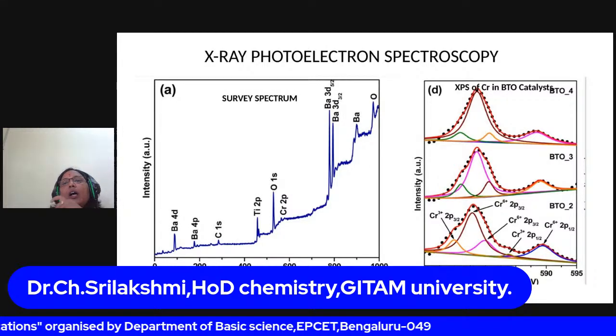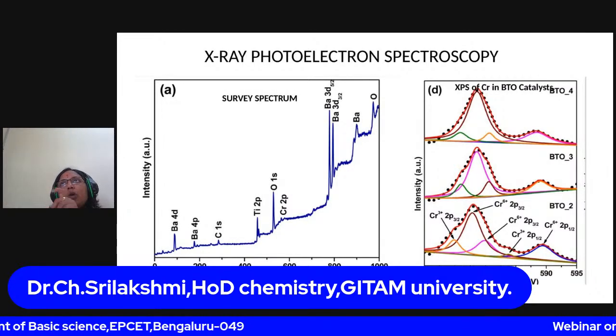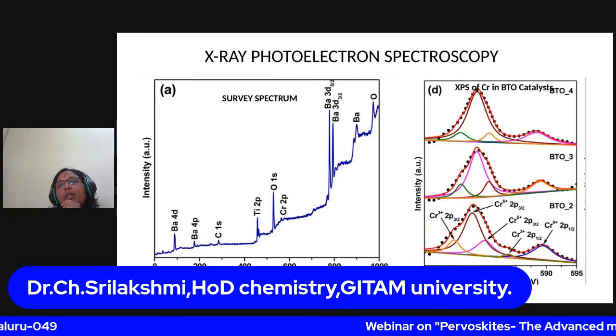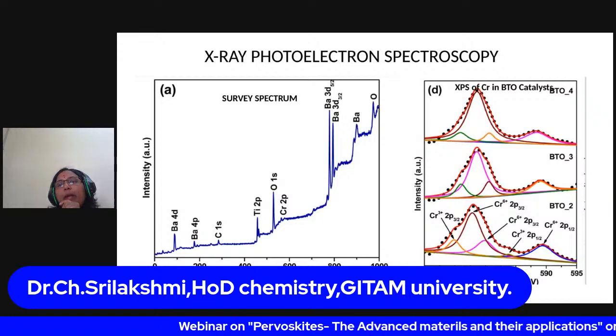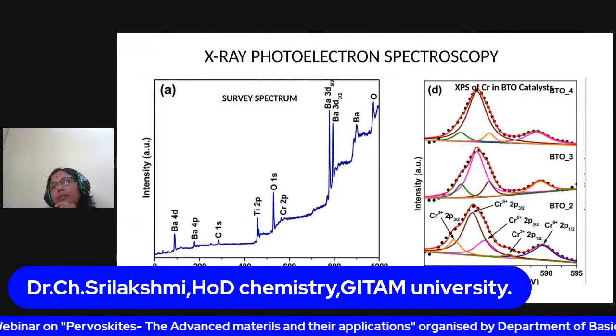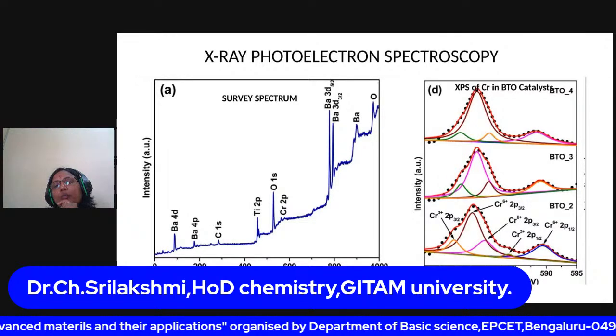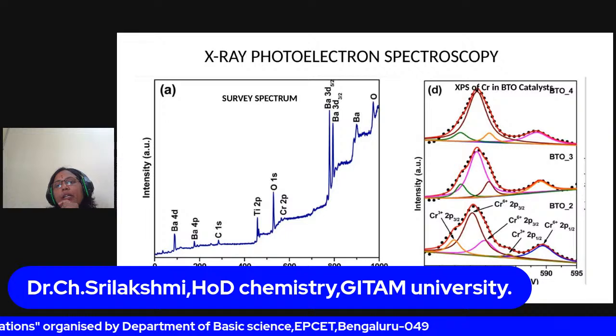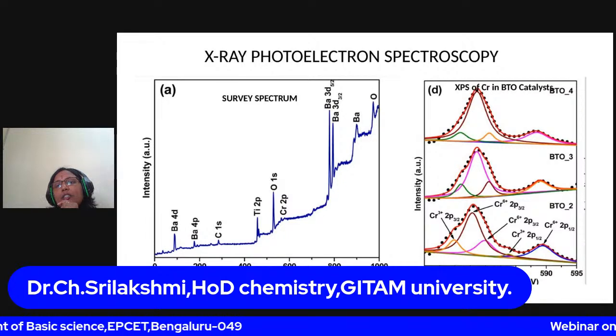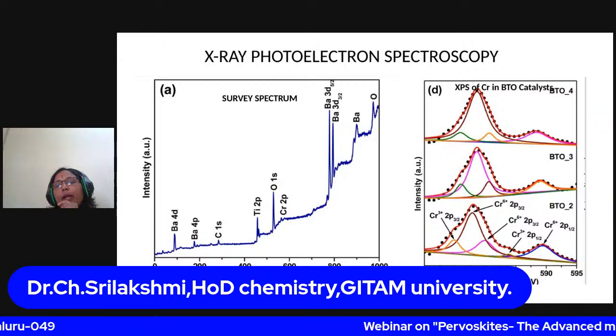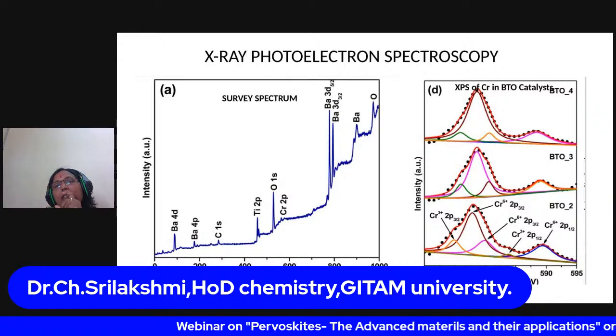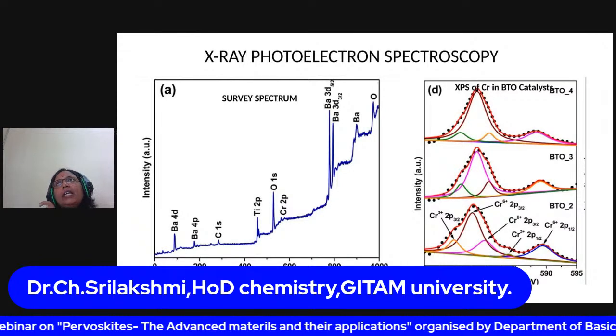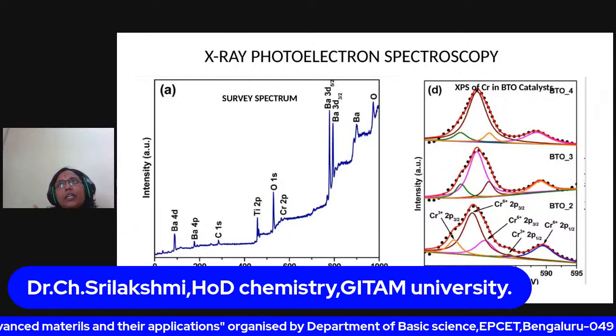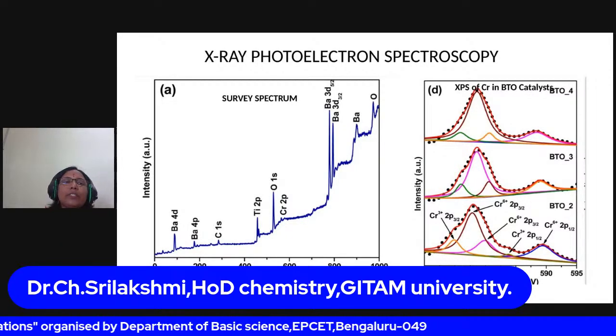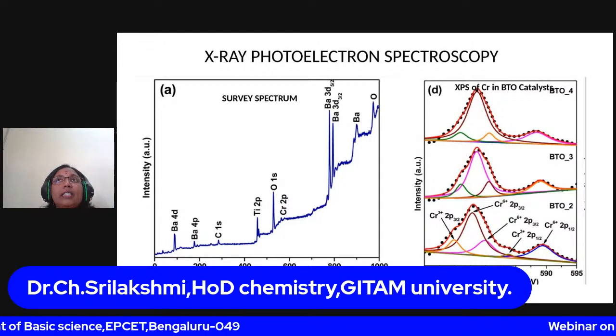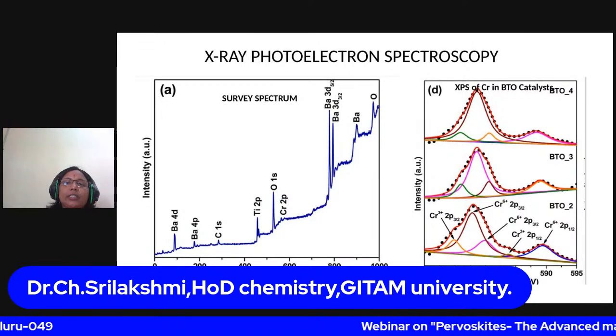Now I have just shown here the chromium. I want to know the oxidation state of chromium in the chromium doped samples. Normally we have observed two broad bands here, one at 577 and one at 589, and these are very broad. So we use a Gaussian fitting procedure, and once we fit, this broad band consists of three small bands, and these small bands correspond to chromium 3 and chromium 6. So my sample is composed of mixed oxidation states of chromium, not a single oxidation state. As we have seen before, this is the speciality of the perovskite structure. It stabilizes the elements in different oxidation states.